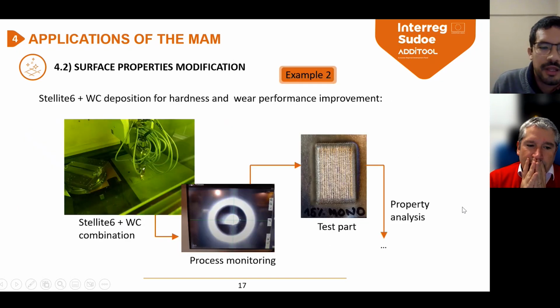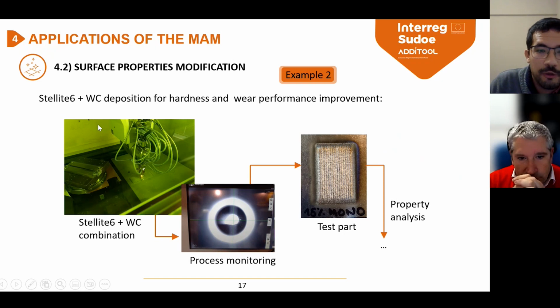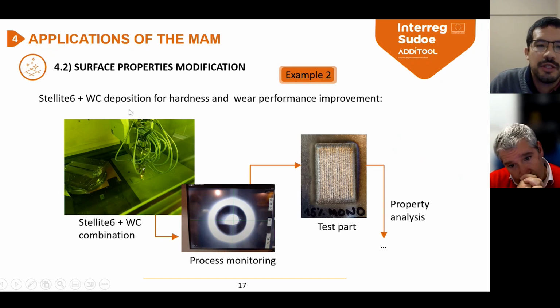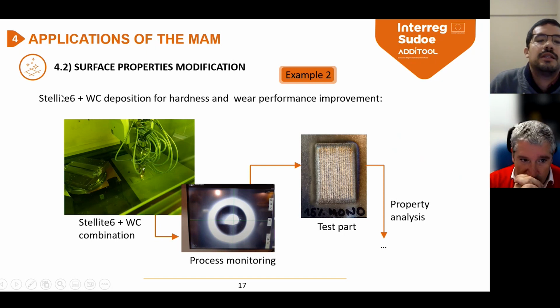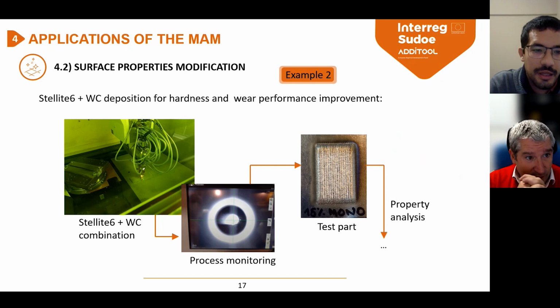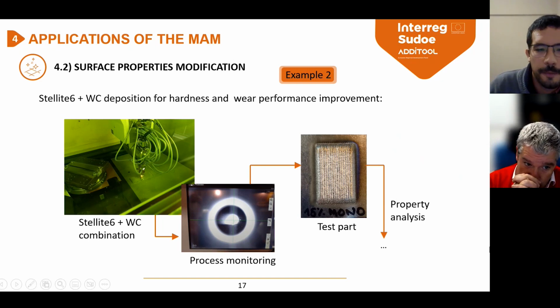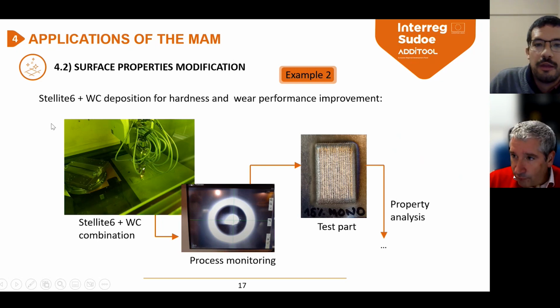In order to show you an example of this metal matrix composite, here I can show you a couple of pictures of a Stellite 6 and tungsten carbide deposition. The Stellite 6 is a cobalt-based hard-resistant alloy. In this case, we have performed the test in the CFAA, which is the High Performance Center that I told you before.